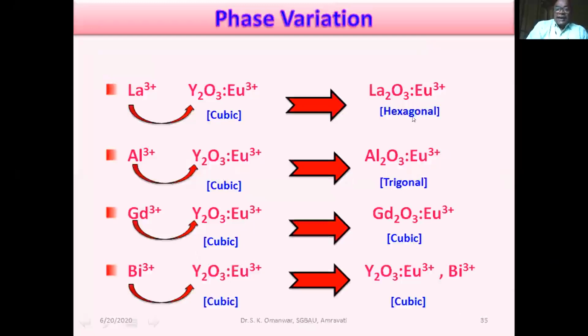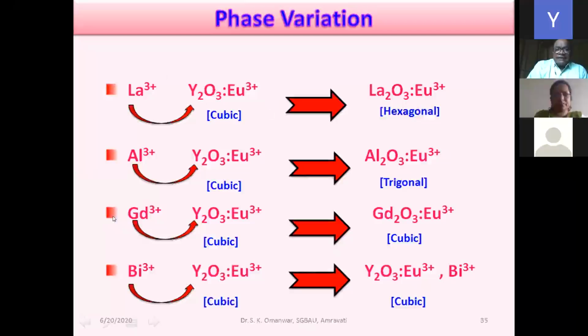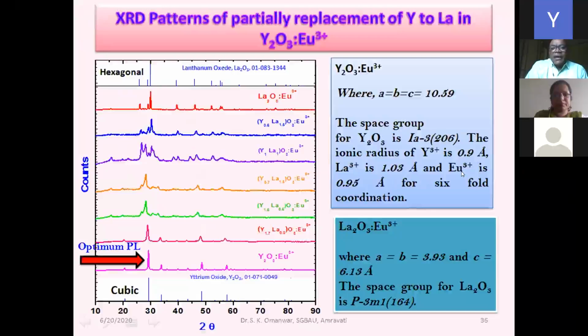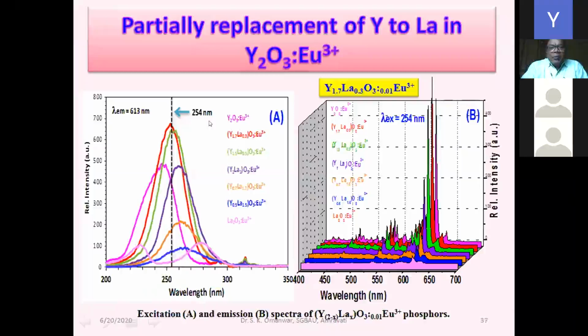So the performance by replacing Y by La, Al, Gd, and Bi is also being seen here. You can see here pure La, then variation of La first, and you see that the optimum PL is obtained earlier, that is Y2O3, and then the performance can be improved through shifting of excitation. See here, 254 nanometer excitation, and emission is monitored at 613, and you will see that the Y2O3 is the pink graph. That pink graph is like this, pink, and this is Y2O3. And this red, you can look at the red. Red is what?